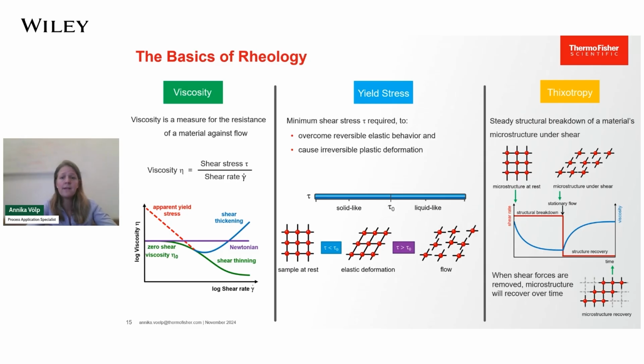Some materials behave as an elastic solid at low shear stresses and as a viscous fluid at high shear stresses. Those materials are called viscoelastic. The transition point, the minimal shear stress required to cause irreversible plastic deformation and flow, is called the yield stress. The onset of flow is hence related to a structural breakdown in such material. The time dependence of the structural breakdown is called thixotropy. It can be measured by applying different steady shear rates onto a material and observing the temporal drop and recovery of the viscosity.